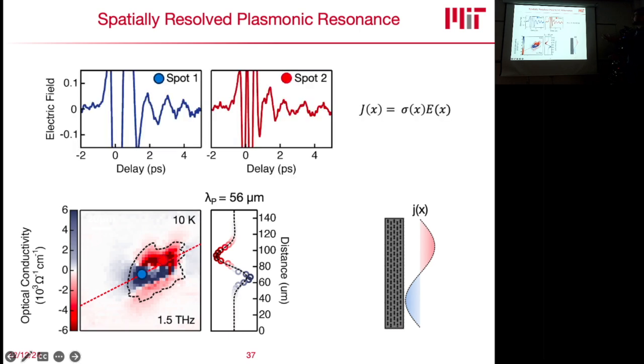And what we can do, and this is the last thing, is to make sure that the currents in these two areas, blue and red, go in different directions, we can look at the electric field that is emitted from here and from here. This is spot 1, which is in the blue region, and spot 2 in the red region. The current should be directly proportional to the electric field. And what we find are these nice sinusoidal patterns, which are a fingerprint of our plasmon. However, if you now overlap them, you find an almost perfectly pi out of phase relationship between these two emitted electric fields, which should be proportional to our current, which shows that in these regions, the currents are going in different directions.